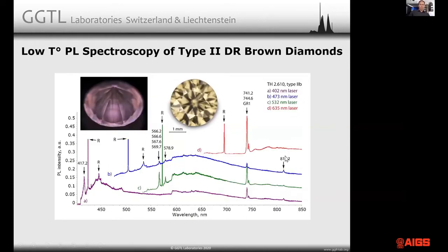Here is the PL of a type 2 diamond. Now I show this is actually a type 2B, hence a boron-containing brown diamond, under different laser excitations. You see the spectrum is quite different, but this is not something that's highly characteristic. Now this is a highly characteristic spectrum for a type 2B stone. Type 1A stones may be very similar to this, but type 1A stones may also be very similar to what you see in other type 1, low nitrogen type 1 diamonds.